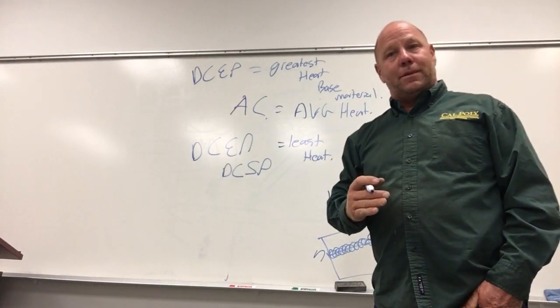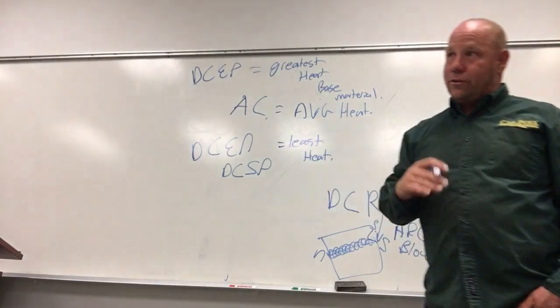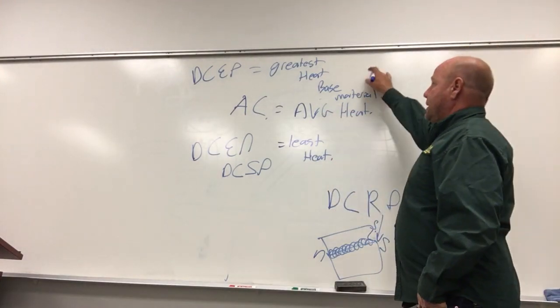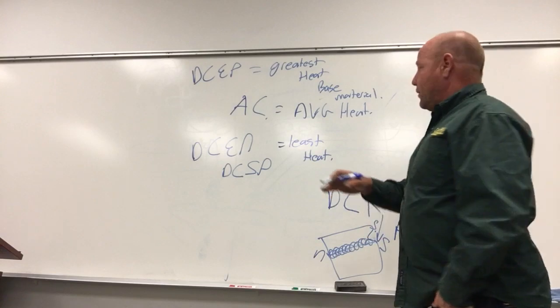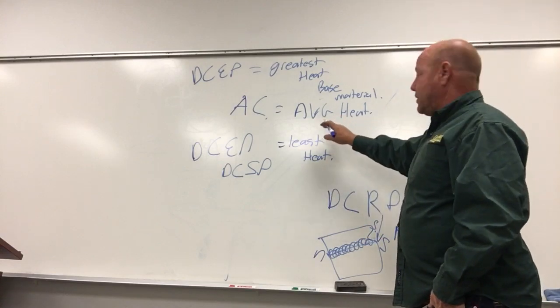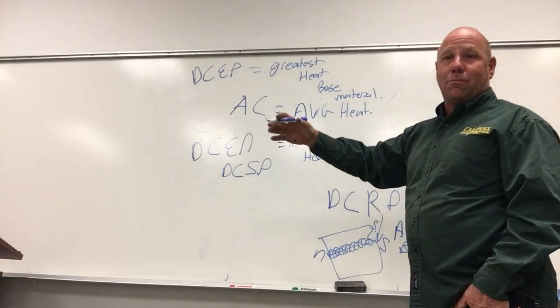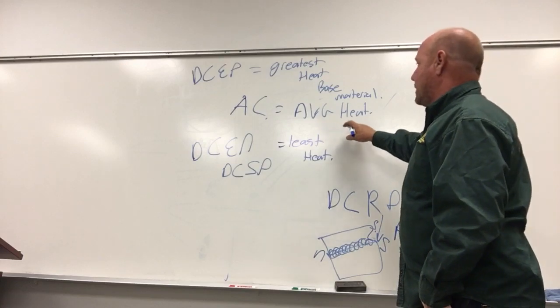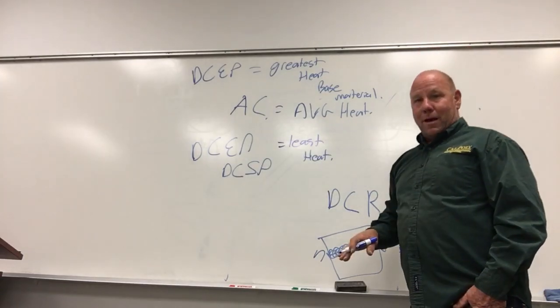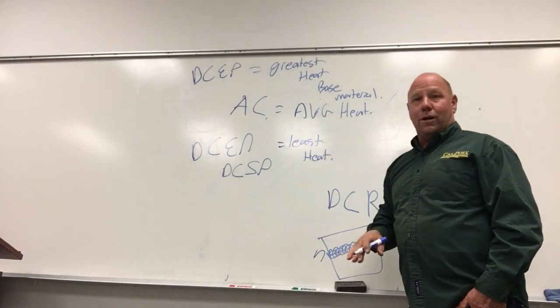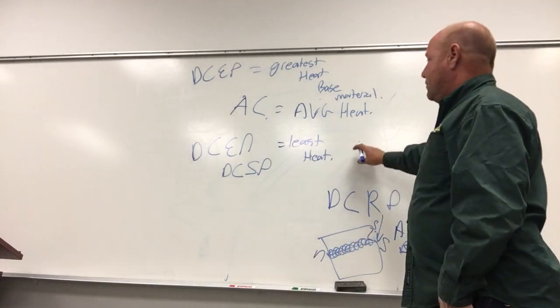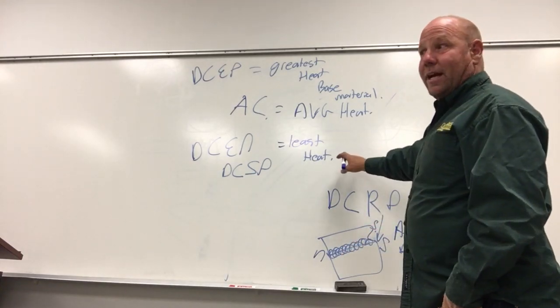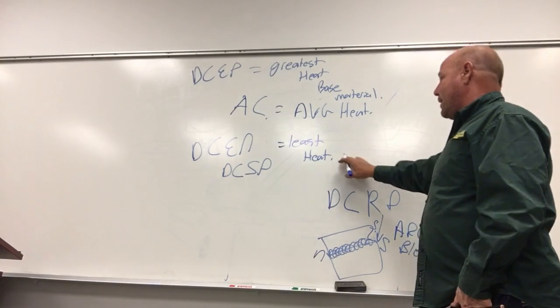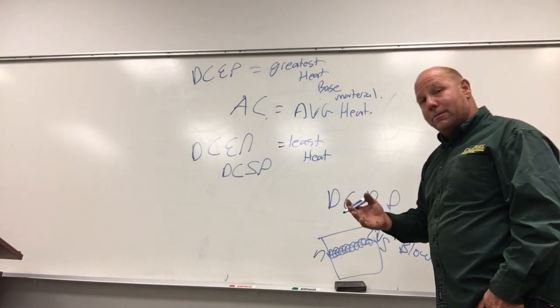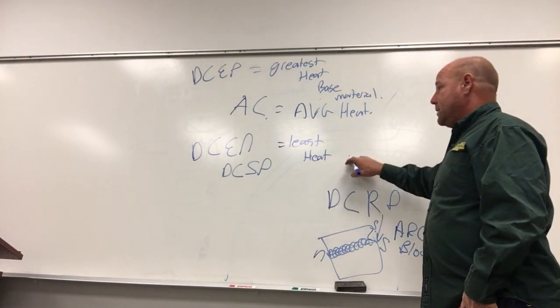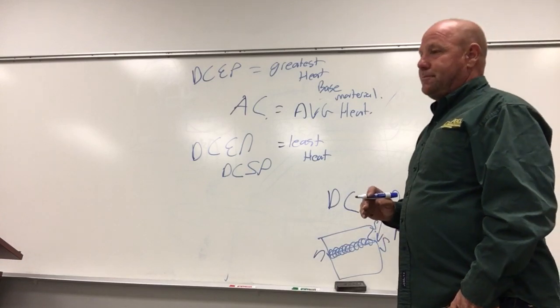So you're welding something hot, you want really good penetration, you're doing a nice root pass, DC electrode positive. You're doing a nice long weld, you have issues, you're starting to develop magnetic properties, you're starting to dig out your weld towards the end. AC will help out a lot with that. Plus a lot of welders come AC. Finally, you're doing something overhead, you're doing something thin on sheet metal, you don't have another machine, you don't have a thin wire feed machine, something like that to get through this, DC electrode negative.